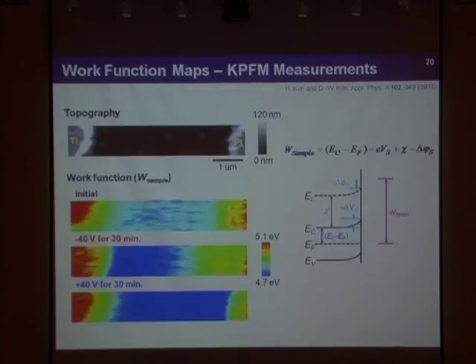So to see what happens there, I obtained work function maps in this junction area. The reason to measure work function is because we can get some idea how the carrier concentration is changed. This is a band diagram—if there is any change of carrier concentration, that will change this value, and as a result the work function should change. So for example, when I apply minus 40 volts to the platinum electrodes, if the carrier concentration is increased, the work function should decrease.